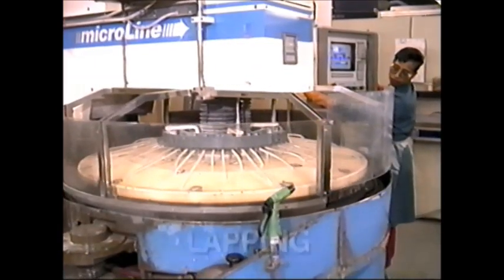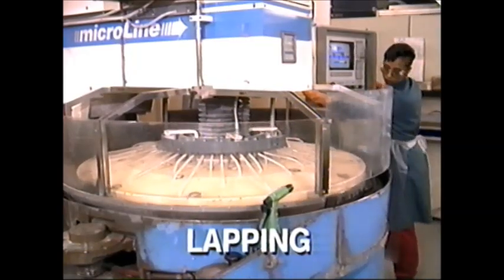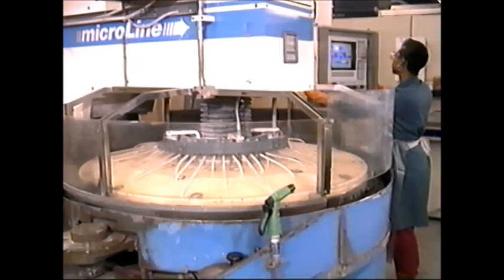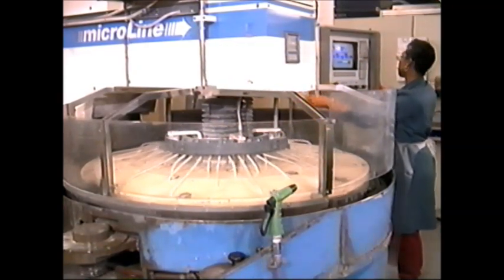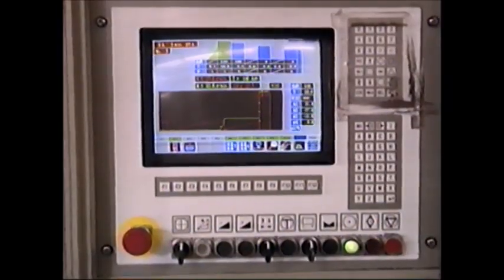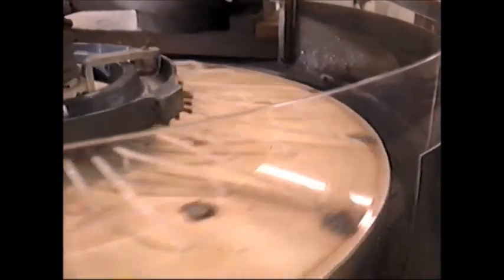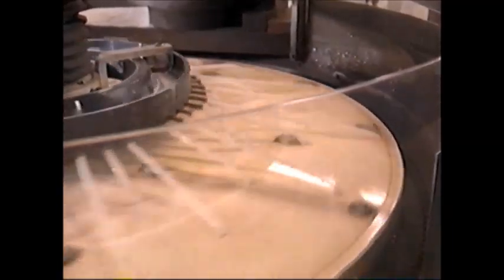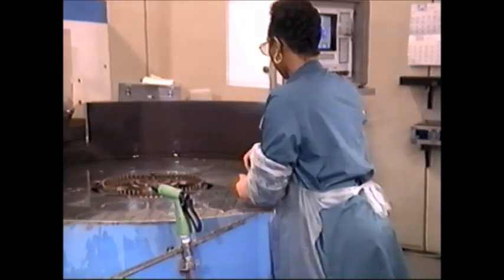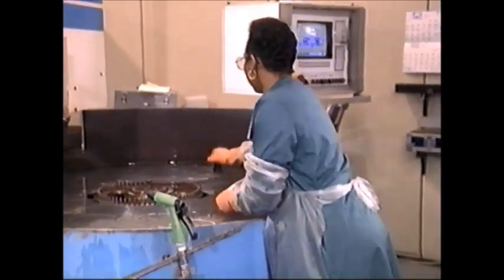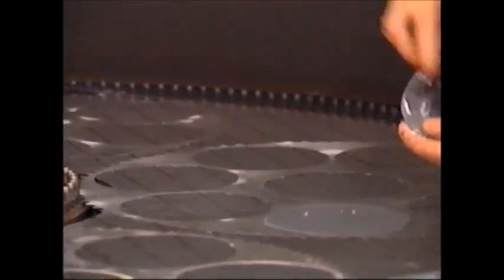The next step in the process is called lapping, during which the wafers are loaded onto a machine which spins them in an orbital motion. This lapping takes place on a table which is rotated between two surfaces as the wafers are lubricated with an alumina slurry. The finished wafers must have a surface flatness of plus or minus 3 microns.